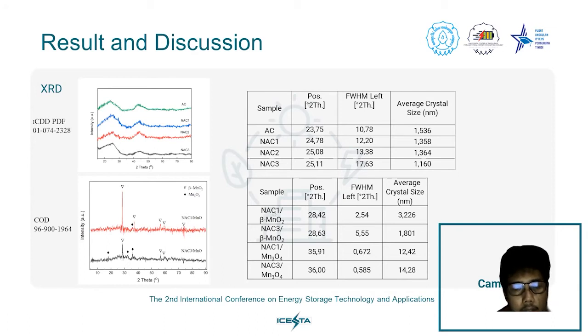Then after that, after we mix it with MnO, we test with XRD too. Then we can see the MnO phase here. The MnO that we got is beta MnO2, and then we got Mn3O4 for the NAC3 MnO. And you can see the crystal size of the MnO here. This is Mn3O4, and then the MnO2 beta phase.